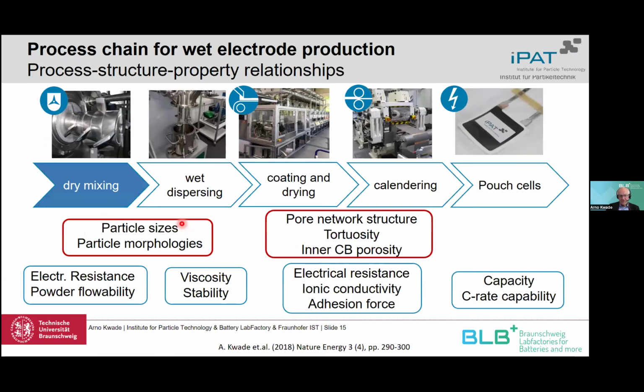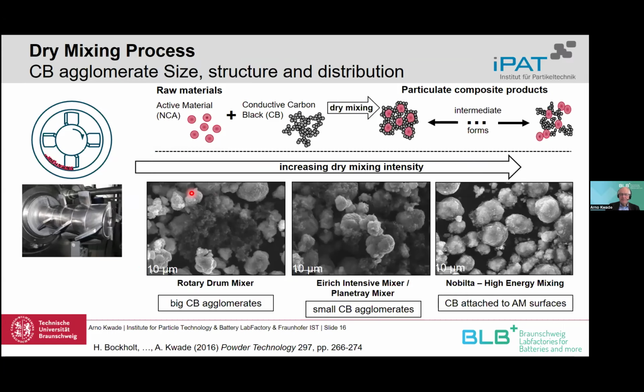And now I want to show how this dispersion index is affected by the dry and wet mixing process. First of all, the dry mixing process: we usually use high intensity dry mixing devices, and we try to coat more or less the active material with the carbon black. That can be done very intensively, that is here on the right side. But it can also be very loose, that is shown here on the left side, where we have only a rotary drum mixer.